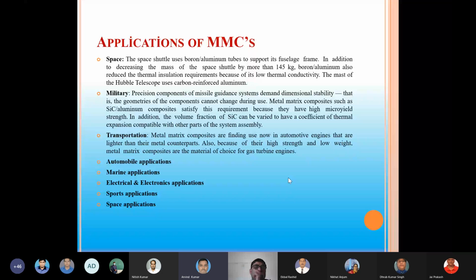Likewise, if we talk about military applications, metal matrix composites such as silicon carbide aluminum composites satisfy this requirement because they have high microyield strength. In addition, the volume fraction of the silicon carbide can be varied to give a coefficient of thermal expansion compatible with other parts of the system assemblies.